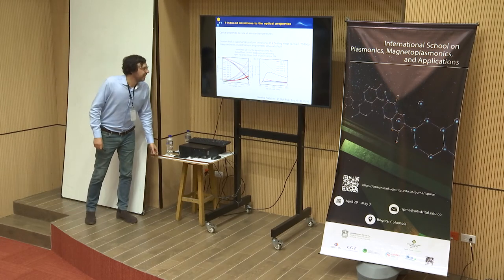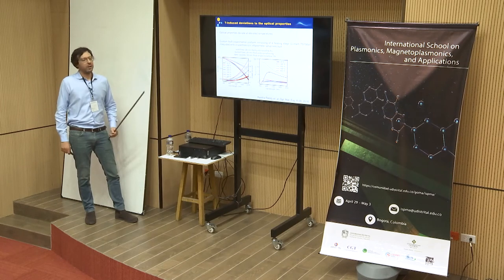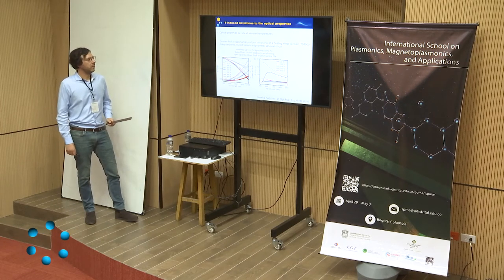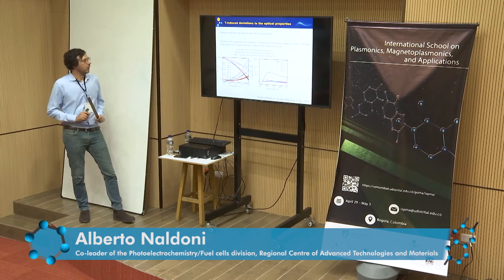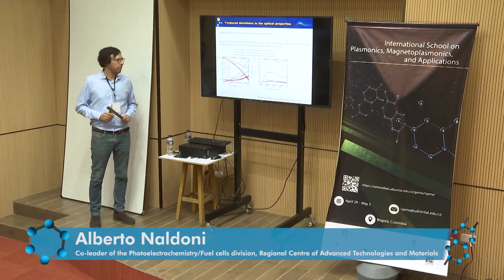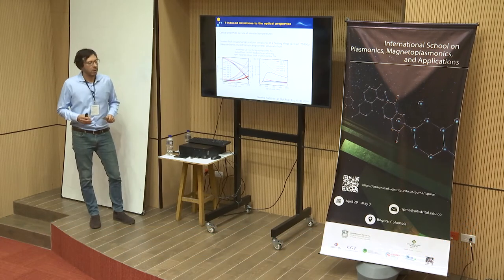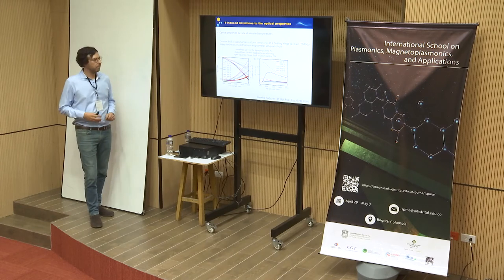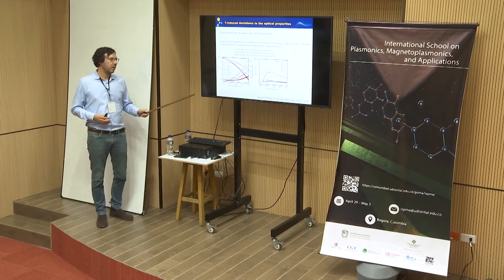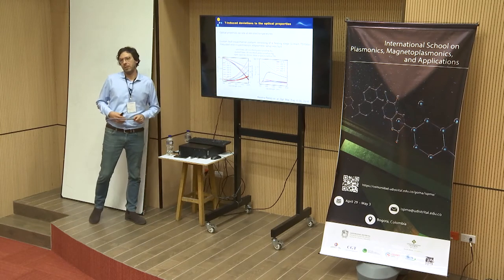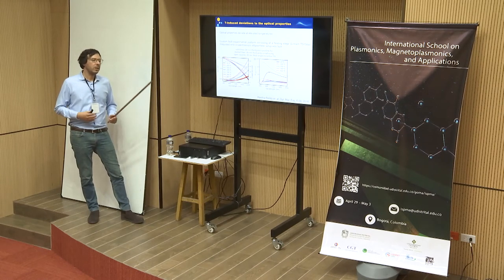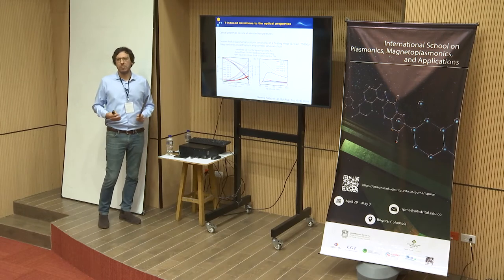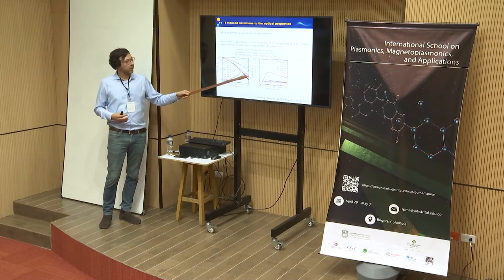This example is very interesting to me because what they did was a simple experiment. They have an ellipsometer and they measure and retrieve the epsilon prime and double prime from the ellipsometry measurement, and then they compute the quality factors for localized surface plasmon resonance or also propagating plasmons. And what was interesting was that at very high temperature, the quality factor of the noble metals, like gold and silver, really deteriorates. The quality factor of other materials like metal nitrides instead remained very similar to the quality factor of the noble metals.